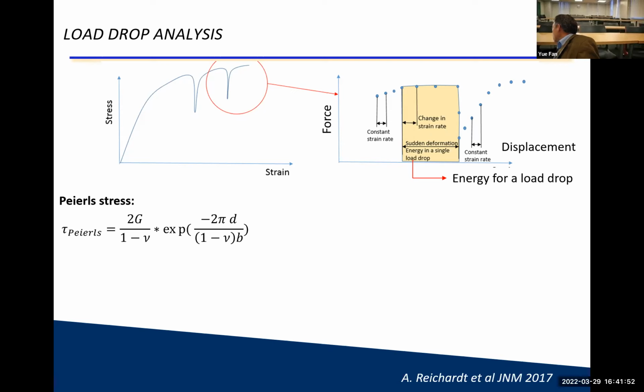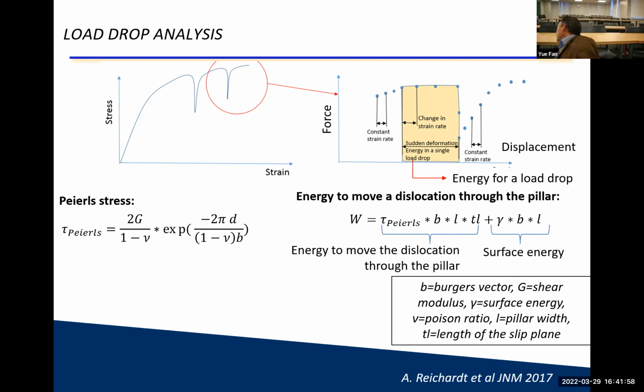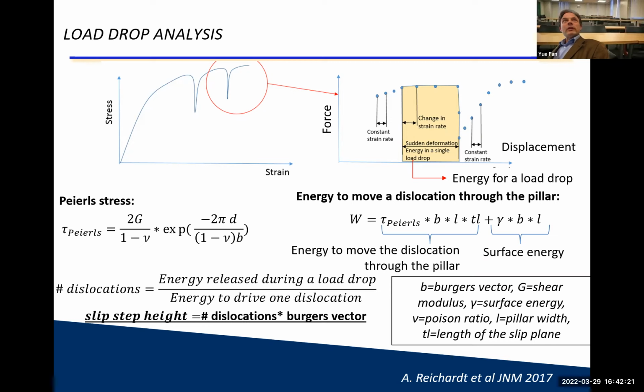And so then I use this energy and put it in correlation to the Peierls stress, which is the stress it takes to drive a dislocation through the lattice. And then I take my Peierls stress and multiply essentially with the dimension of my pillar and the surface energy term, because you create new surface at that point. And that's the energy it should take me to create that load drop. So this is what I measure, and this is what it should be. And when I divide one versus the other, then I can calculate how many dislocations take part in that event, because one dislocation causes this much deformation. And so the total energy divided by the energy of one dislocation gives me the number of dislocations. And so the number of dislocations times Burgers vector should give me the slip step height.